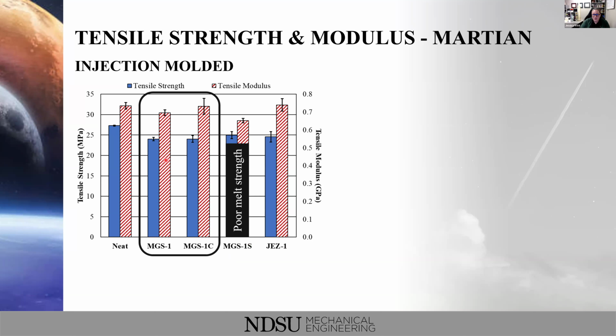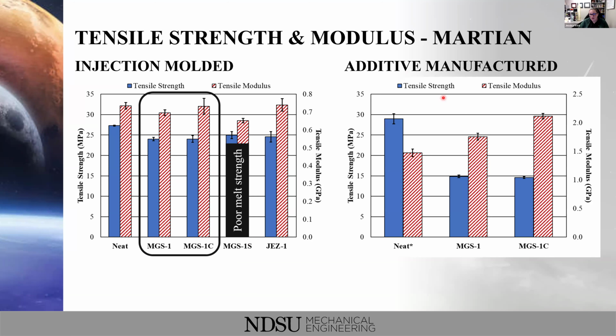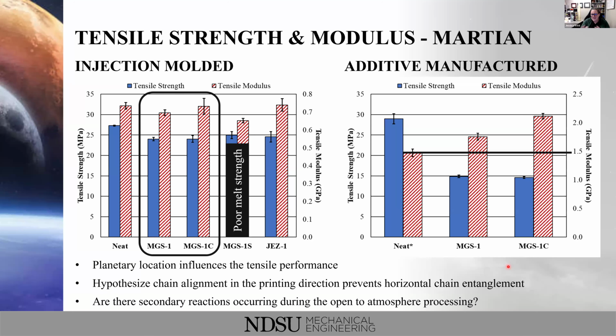So we only moved with our global, our MGS1, and that simulant had a little bit more clay in it. We took those two simulants and moved them forward to our additive manufacturing testing. We did additively manufacture our tensile bars, and when we got to these results, some really interesting things occurred. The very first thing we noticed was our neat polypropylene, which had a modulus of around 0.75 gigapascals, was now above 1.5 gigapascals. We thought, that's really interesting. We made our material stiffer when we additively manufactured with it.